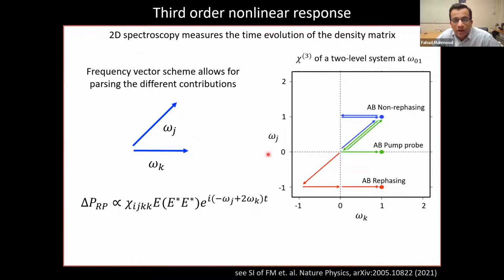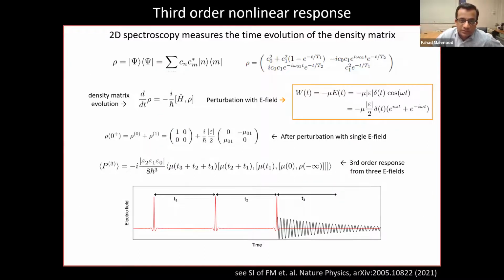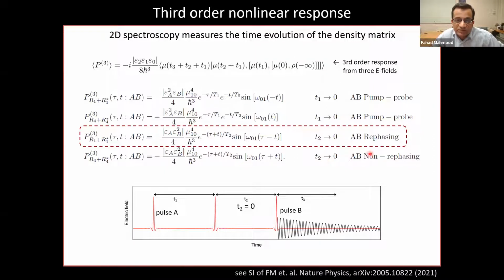So for example, one response that you measure in this 2D spectroscopy is known as a rephasing response, which occurs at this particular combination of the two frequencies. And as I'm plotting my response as a function of omega j and omega k, the two frequencies I'm sending in, this response will occur at some other particular point in this frequency space. Okay. So how is this connected to actual lifetimes or scattering rates that I was talking about? To see that, we're just going to model our system by, let's say, an ensemble of two-level systems. Each two-level system has a T1 time, which is a relaxation time, and then a decoherence time T2. And so I can write down this density matrix for my two-level system, calculate its nonlinear polarization, and without walking you through the details, if you work out the math, you'll eventually see that this rephasing peak that I was talking about encodes information about the decoherence time, T2, okay?